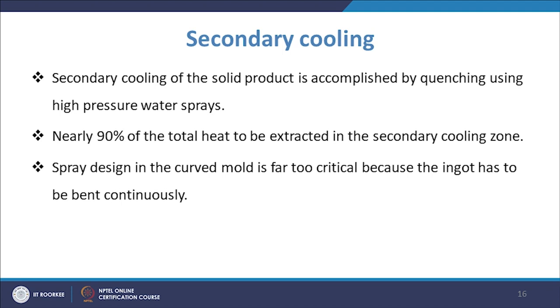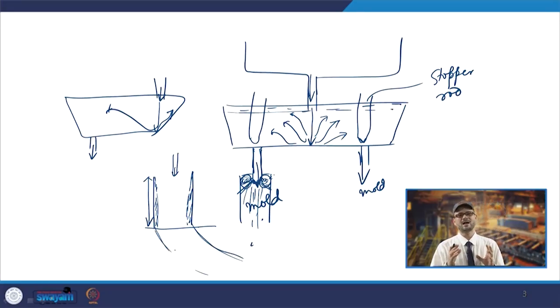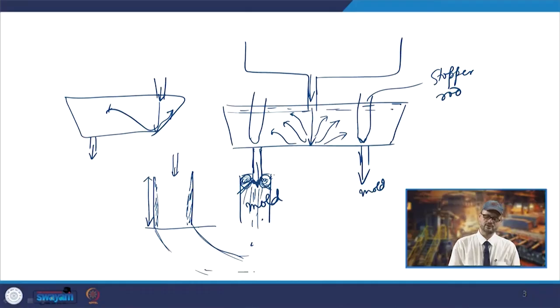After that you have the secondary cooling of the solid product, which is accomplished by quenching using high pressure water sprays. So 90% of the total heat is to be extracted in that secondary cooling zone, which starts after the mold. Spray design in the curved mold is very critical, because the ingot has to be bent continuously. So it is bending, and that is another challenge, as you will have less area here, more area there. So you have to have proper cooling so that uniform structure and uniform properties are ascertained. And then finally it will go, and ultimately we cut it.